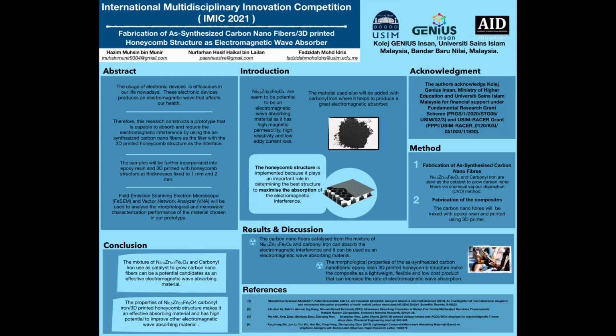Nickel zinc ferrite seems to be potential as an electromagnetic wave absorbing material as it has high magnetic permeability, high resistivity and low eddy current loss. The material used also will be added with carbonyl iron, which helps to produce a great electromagnetic absorber. The honeycomb structure is implemented because it plays an important role in determining the best structure to maximize the absorption of the electromagnetic interference.